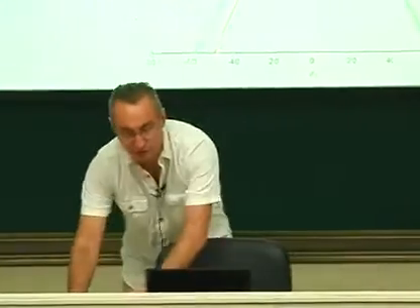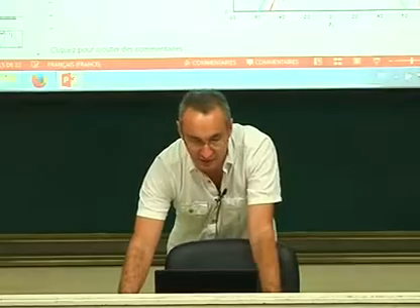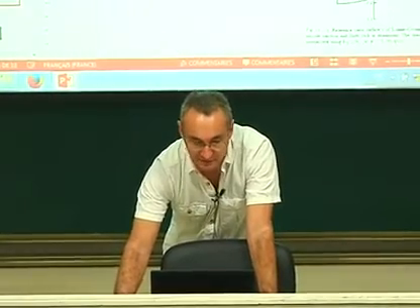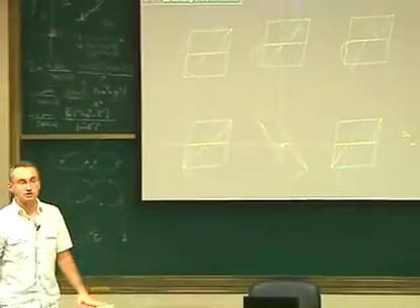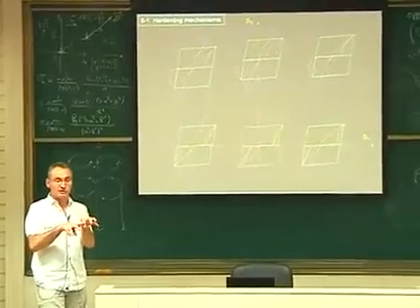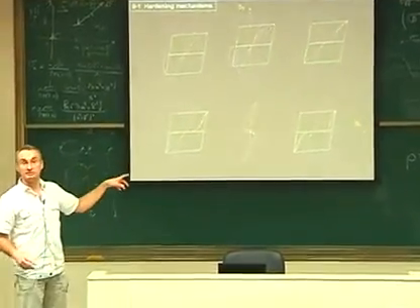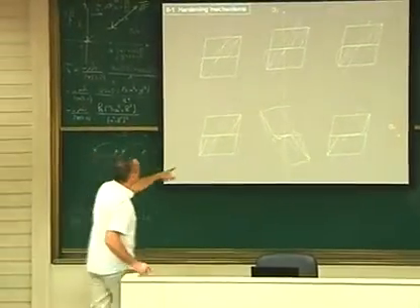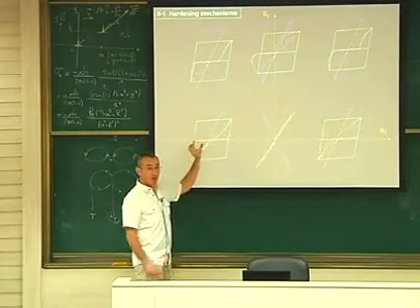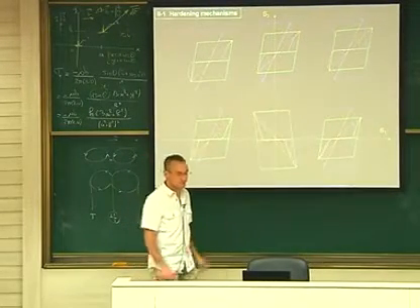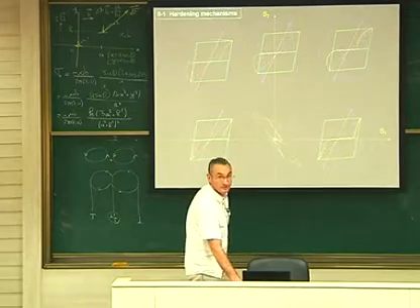Okay, so I come back to my slide. I will add these curves in my PDF, so you will have them. Okay, and I come back to this one. So you see this, and you see how we destroy a junction, and you can see the mechanism. The mechanism to destroy a junction is not breaking. It's not a junction which suddenly breaks. It's what we call unzipping. You unzip your dislocation junction. You see that it is moving like that, unzipping slowly, up to the time it will be a zero-length junction.